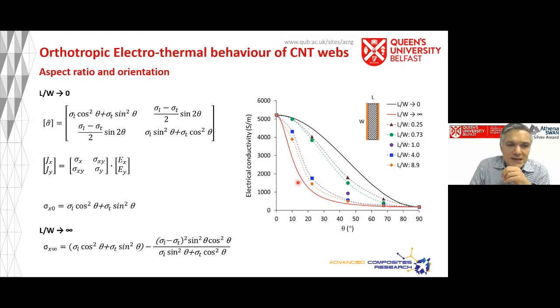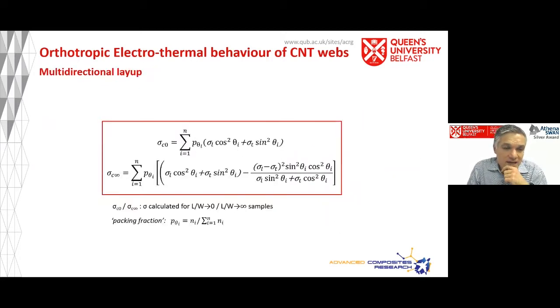So in other words, we can predict the sort of conductivity you are likely to get from an orientation of that web. Now, of course, we can lay them in different directions, and then again, by analogy with what you would do with a structural directional orthotropic material, you can add these up. You can add the contribution of each orientation, and then you can measure or predict the conductivity of that stack.